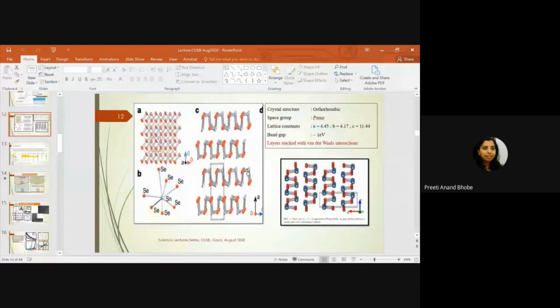If you look at the crystal structure, then along A axis or B axis and C axis, the figure that is shown at the right lower corner here. If I look at the C axis of it, then all the layers are connected. If I just go along the C axis, then the atoms are connected by chemical bonds. If I go along A axis, certain atoms are connected along by chemical bonds, then there is a gap because there is a van der Waals interaction, then the next layer comes. Similarly, in the B axis also, it's one layer upon another layer, which is held by van der Waals interaction and not a strong chemical bond, like covalent or ionic bond. It is a van der Waals interaction.